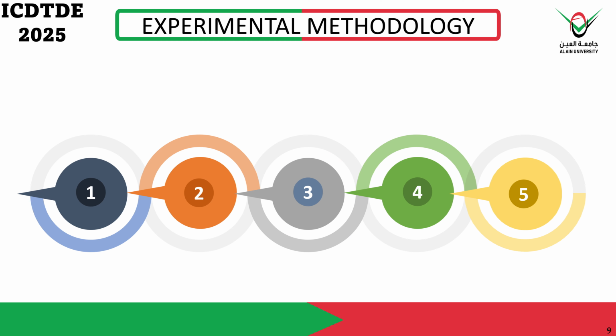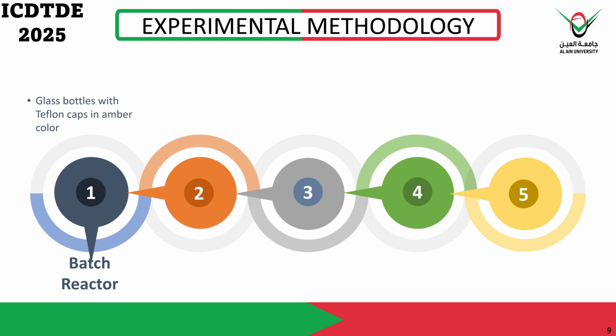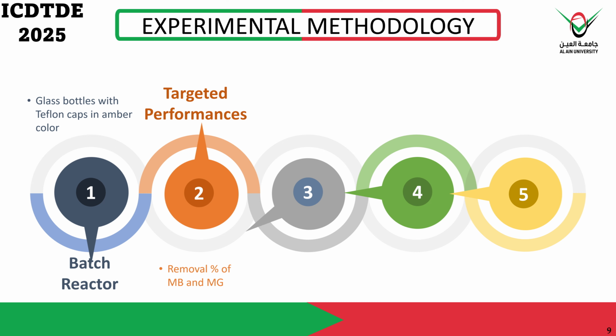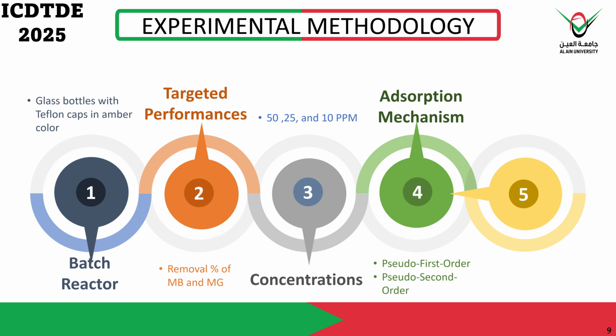Experimental methodology: first, a batch reactor where we use glass bottles with Teflon caps in amber color. Our targeted performance is the removal percentage of both MB and MG. We use different dye concentrations of 50, 25 and 10 ppm. The adsorption mechanism: was it pseudo first order or pseudo second order? Lastly, we analyze the adsorption behavior using kinetic isotherms to see whether it's the Langmuir model or the Freundlich model.